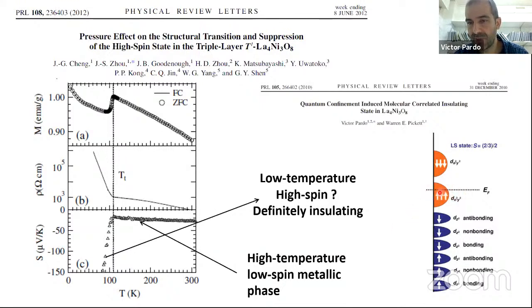At the Fermi level, you would have a partly filled band, and the big weight at the Fermi level would be the x squared minus y squared electrons, just like in the cuprates. And as I said before, from the data of the resistivity, you didn't know much about the behavior of this material. That's why Goodenough's group got rid of the contribution of the grains by measuring the thermopower. So what they saw is that at low temperatures, it is indeed an insulator, but at high temperatures, it is a metal. And with the thermopower, you see it very well.